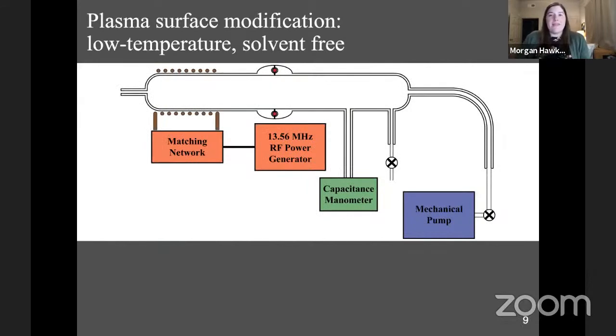Okay, so here's a schematic of the inductively coupled plasma reactor. This is a tubular cylinder. The first thing that we do is open this plasma reactor. There's an O-ring joint here, and we can add in the polymer material we want to modify anywhere in the chamber. So next we use a mechanical pump to create a low pressure environment inside of the reactor. After that, we flow in a gaseous precursor. So this could be like a pressurized gas cylinder, or it could be the vapor from a high vapor pressure liquid. And this gas that we flow in is referred to as the plasma precursor.